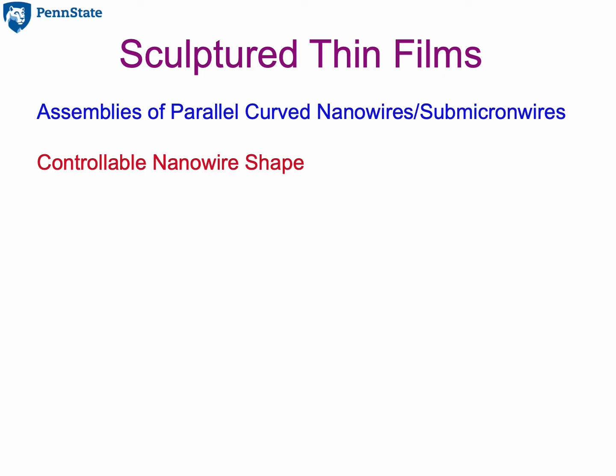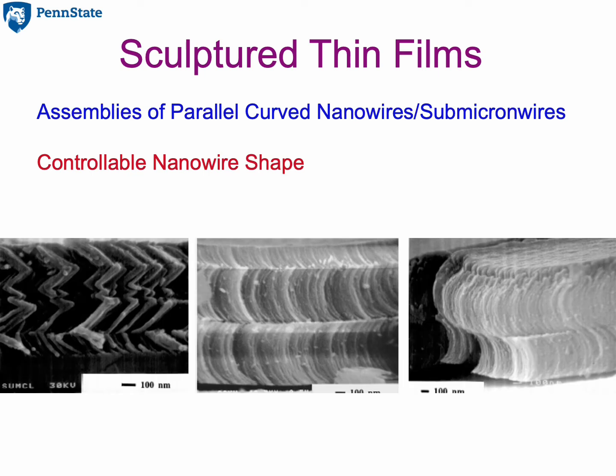These are assemblies of parallel curved wires whose diameters are on the nanoscale or the submicron scale. The shapes of the nanowires are controllable, with the stipulation that the nanowires must grow away from a substrate. Here you see scanning electron microscope images of some sculptured thin films. The shaped nanowire morphology is clearly evident therein. On the left, you see a sculptured thin film which is made of nanowires that seem to be shaped like chicken bones. Then in the middle, the nanowires are shaped like C's. And then on the right side, you see nanowires that are shaped like S's.